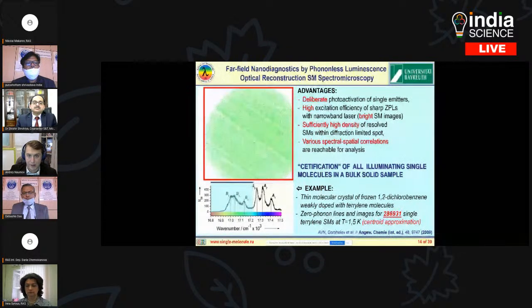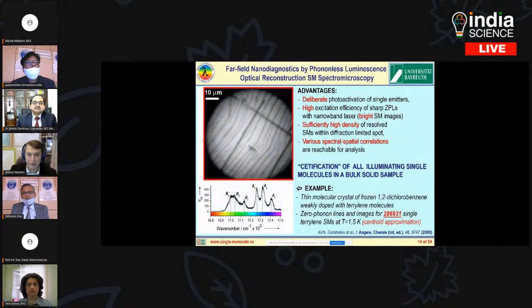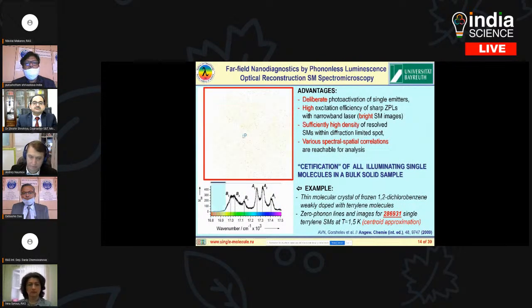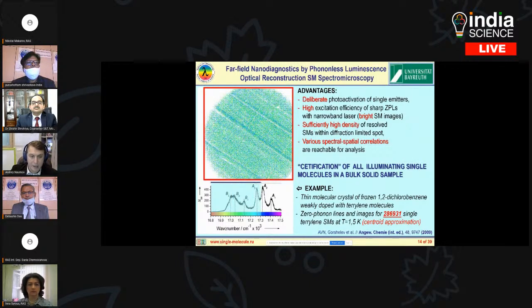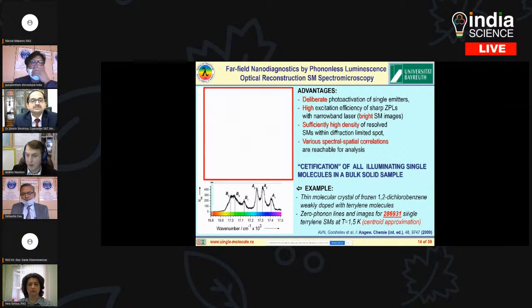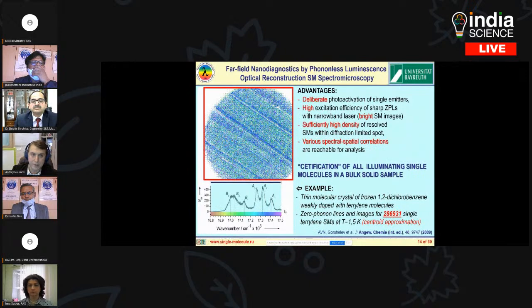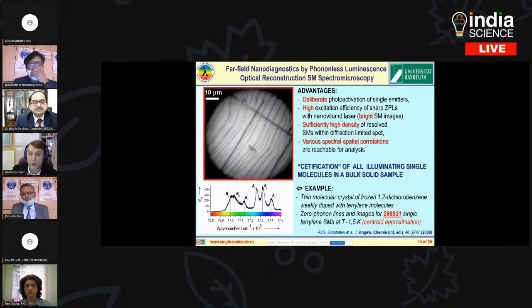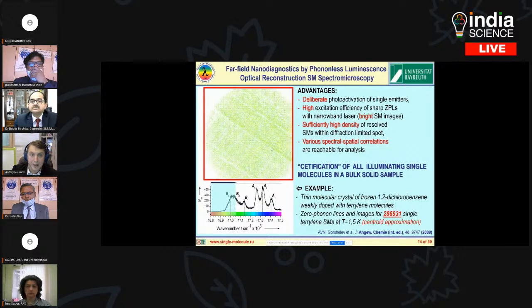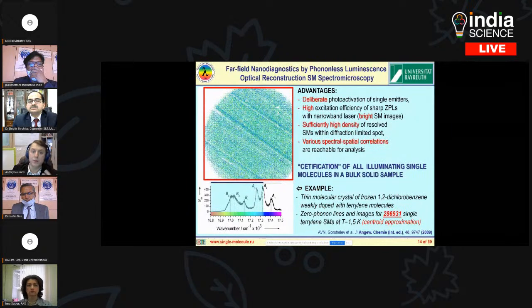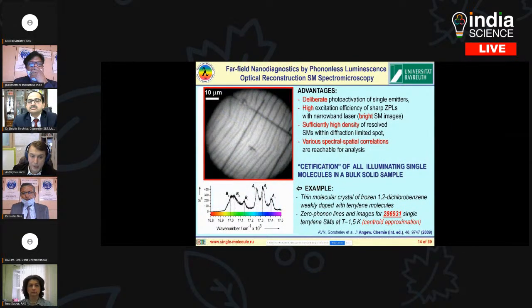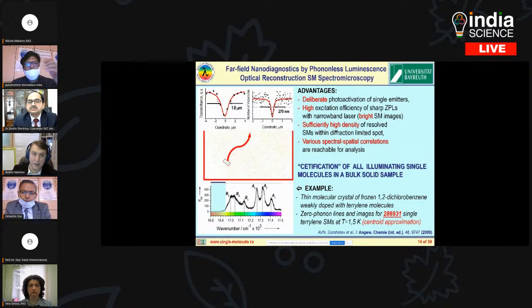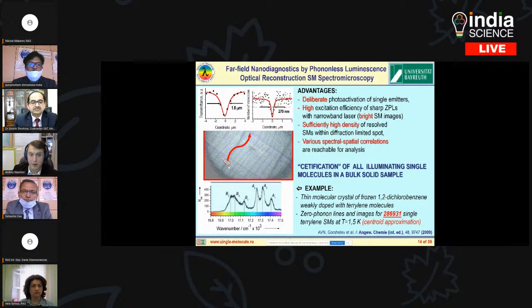You see, I have a thin film, a polycrystalline film. It's frozen orthodichlorobenzene, some chemical structure. And I scan my laser, and I detect images and spectra for about 300 thousand single label molecules. These are so-called terrylene molecules. Then I realize image processing for each molecule, and I find the spectrum. And now I can realize so-called multicolor diagnostics of my sample, because I can visualize, for example, here you see, the shape of a crack in this part of my film.